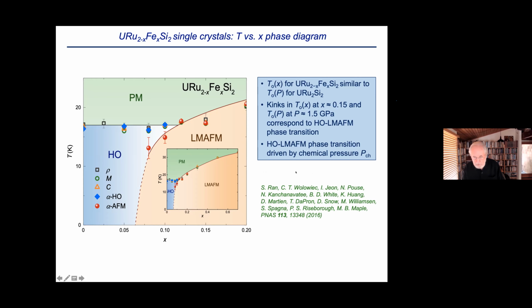Now, in retrospect, and I'll come to this at the end, there is a chemical pressure effect, of course, but really what appears to be driving it is that the hybridization of the iron d states with the uranium 5f states is much stronger than it is for ruthenium. So by replacing ruthenium with iron, you're increasing the hybridization, and that, after all, is what must really be driving the transition. Of course, the hybridization would also increase under pressure. But in the beginning, this is what we assumed. I think it's more complicated, and I'll come back to that later.